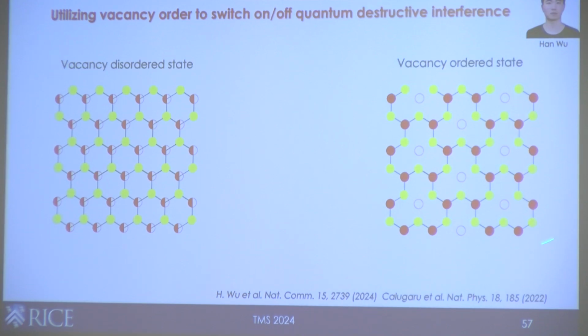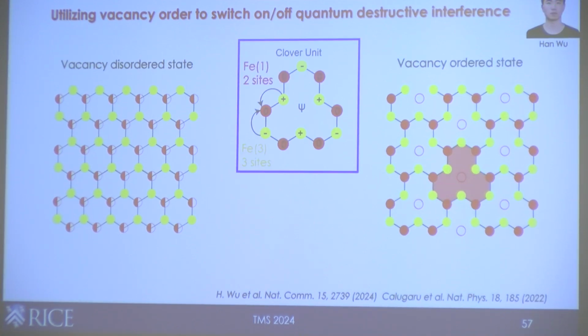So you end up with something like on the right-hand side. And then you may recognize that this is a repeating unit of this shape, which my student Han named the clover lattice. And it's special because it is a bipartite lattice, which means that the nearest neighbor hopping is always between two different sublattices, number one. And number two is that the number of sites belonging to the two sublattices is different.